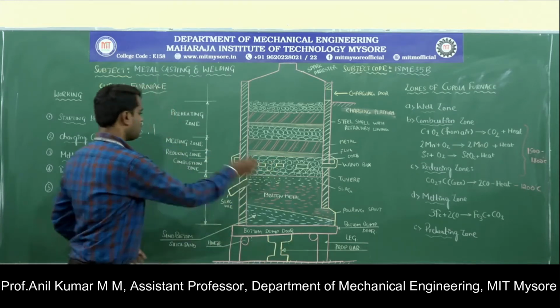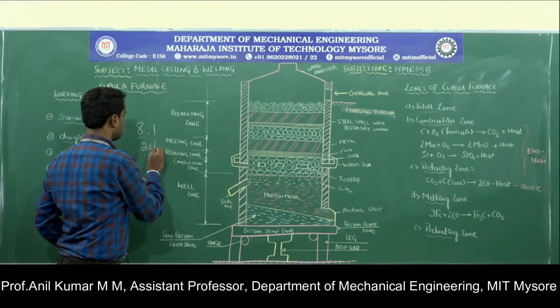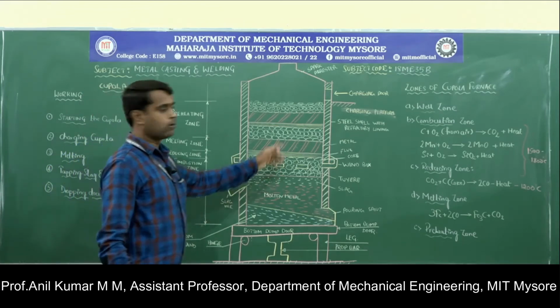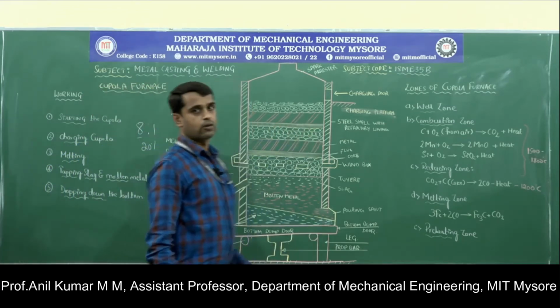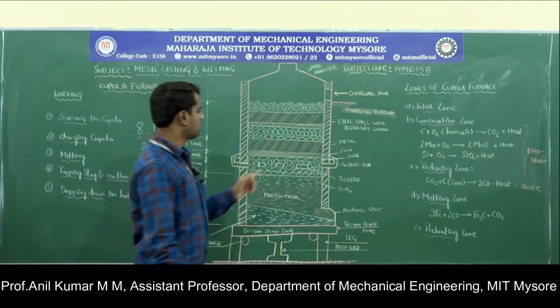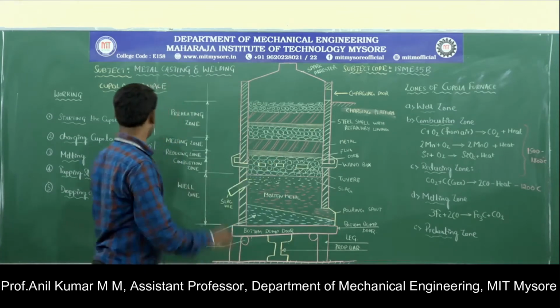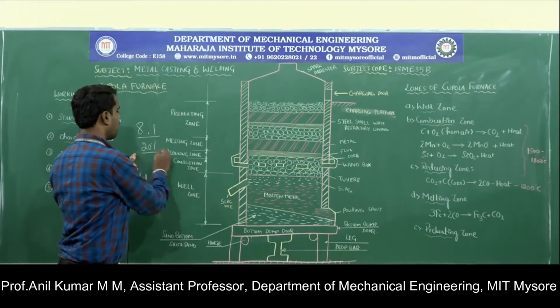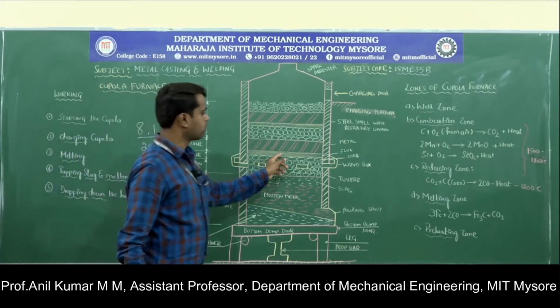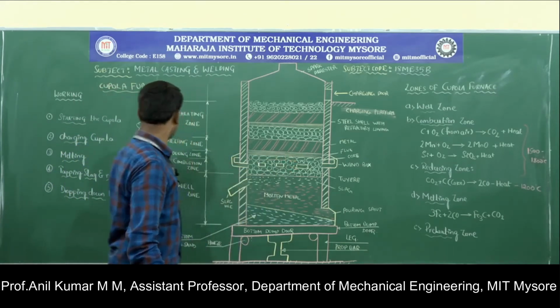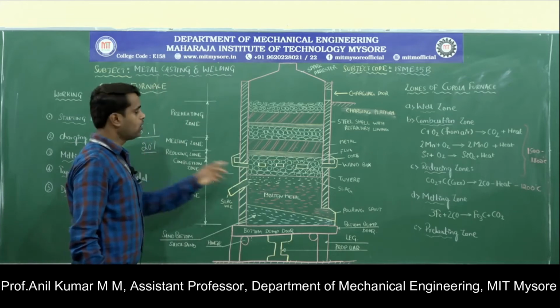And then the flux is around 20% of the weight of the coke that will be added inside the furnace. The commonly used flux material is limestone. The iron to coke ratio is 8:1, and the weight of the flux added inside the furnace is 20% of the weight of the coke.